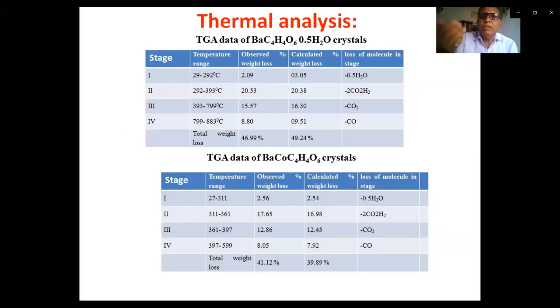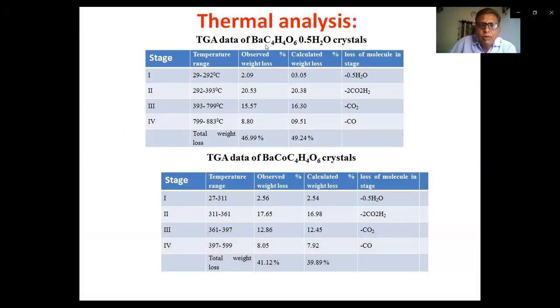In the TGA when I dope cobalt in barium tartarate, I also get four stages. Temperature ranges are 27 to 311 to 397 to 599. The observed percentage loss is 41.12% and the calculated weight loss is 39.89%, and the loss of the molecules is shown in a chart. But in this case, when I took cobalt in barium tartarate, the observed weight loss decreases, and the calculated weight loss also decreases here.